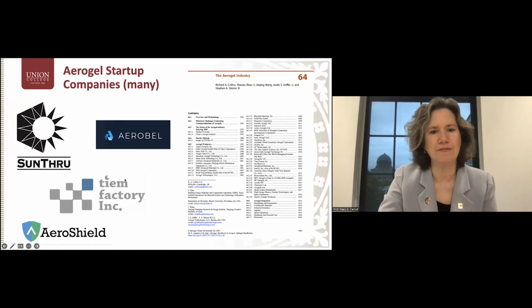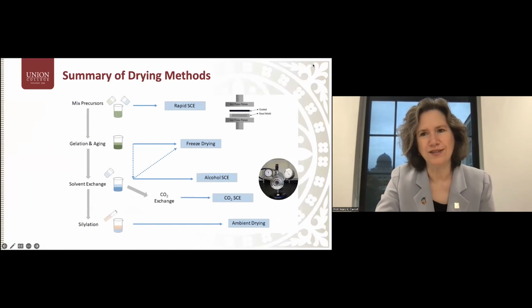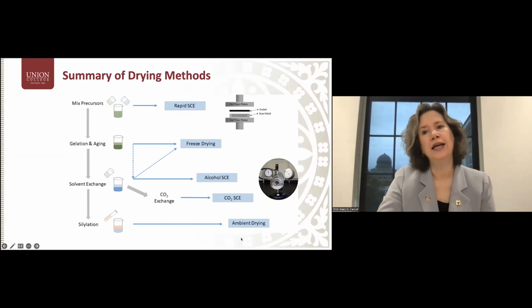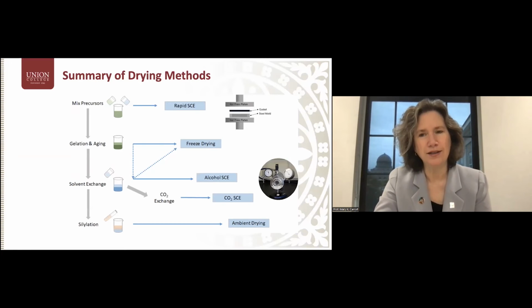And so I'd like to emphasize something that's different about them, and that's that those three companies, SunThru and AeroShield and Tiem Factory, are each using different drying methods. So again, our method is the rapid supercritical method with the hot press, mixing chemicals, putting them into some sort of contained mold within a hot press. And so we're based on a rapid supercritical extraction method. The group in Japan is making gels, allowing them to age, doing solvent exchange and surface modification and ambient drying. And they are, frankly, able to make larger monolithic aerogels than we are, but to make a very large monolithic aerogel can take as much as a month, whereas our method takes on the order of hours.